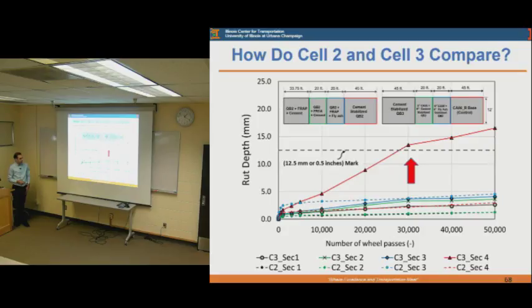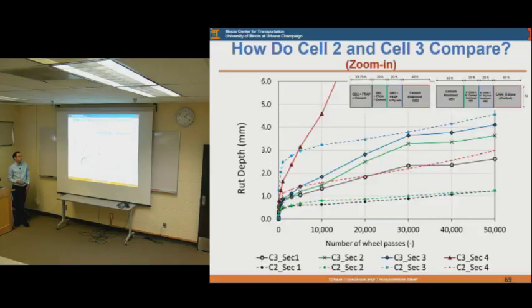And it's not clear here, but I have a zoomed in picture, and it's also very clear for the control section that at one point after 30,000 cycles, we see that the rate of rutting is decreasing. And the main reason for this is actually the drop in temperatures, which led to more stiff asphalt and reduced the rutting of the section. So this is the zoomed in test sections, and now we can compare all the different test sections.